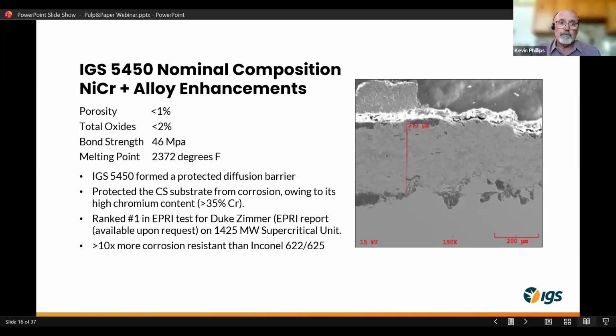As I said, we manufacture all of our own wires in-house. They are specially formulated for highly corrosive environments. Our 5450 is our main go-to alloy for the higher sulfidation situations that you would find in recovery boilers. It has a very low porosity level of less than 1%, less than 2% of oxides. So what this is really doing is it's providing you a very protective diffusion barrier that's going to protect that substrate from the corrosion, also from the fact that it's 35% chromium, which is very impervious to the corrosive elements.